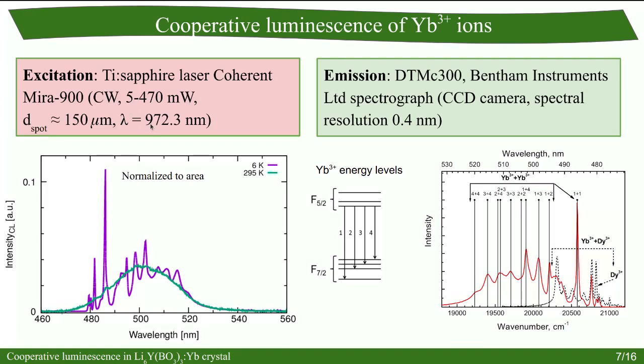And we measured our spectra with an excitation wavelength of 972.3 nanometer, and the spot diameter at the sample was 150 micrometer. The emission was recorded by a spectrograph with a CCD camera with a spectral resolution of 0.4 nanometer. Two spectra, as an example, are shown here.